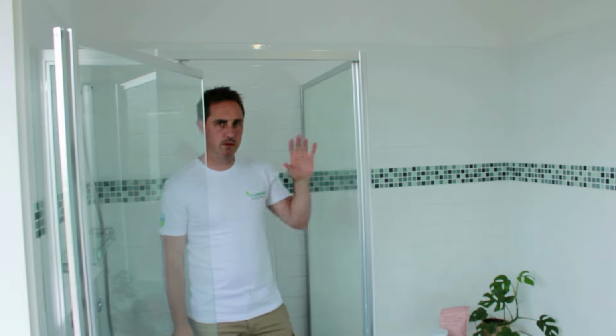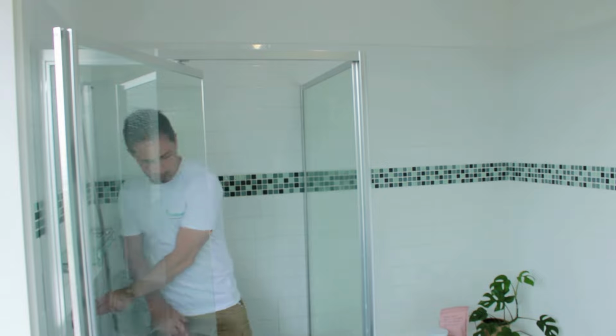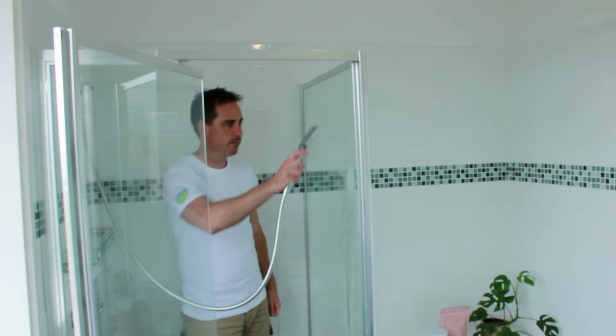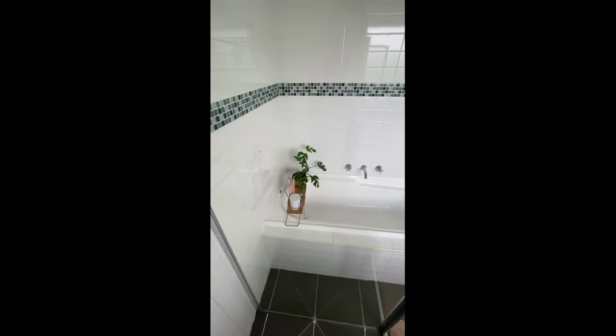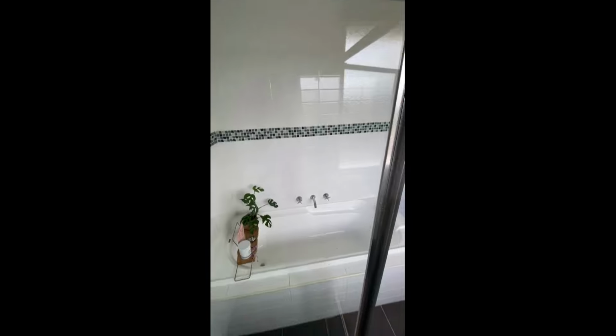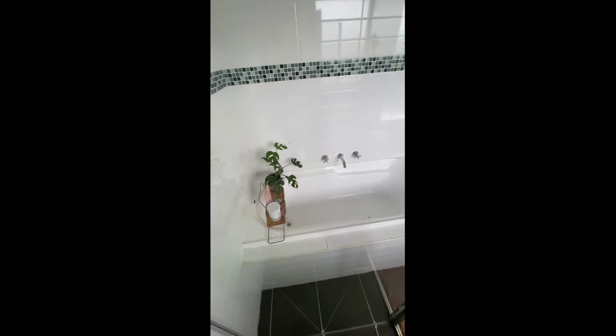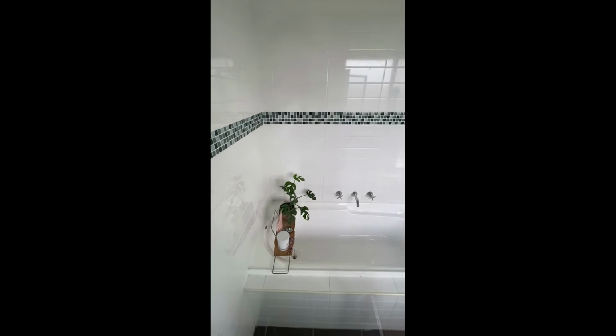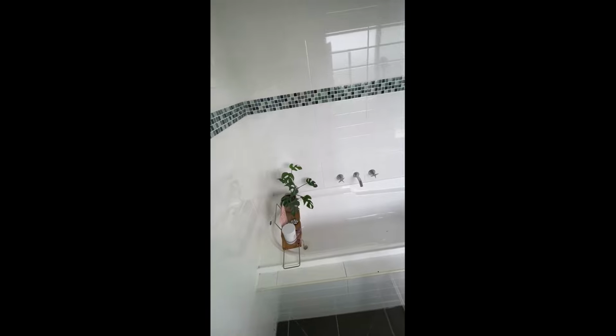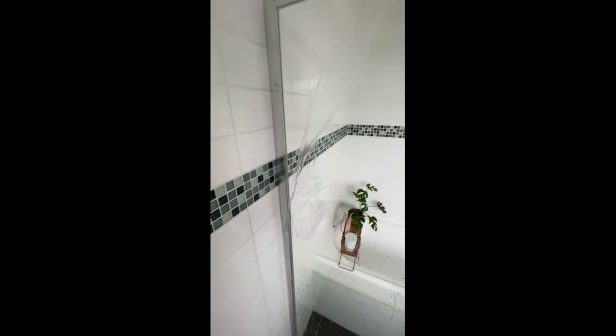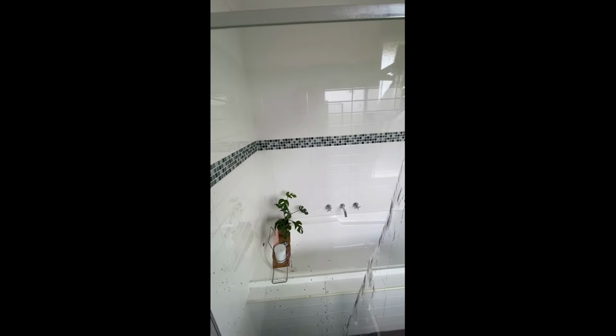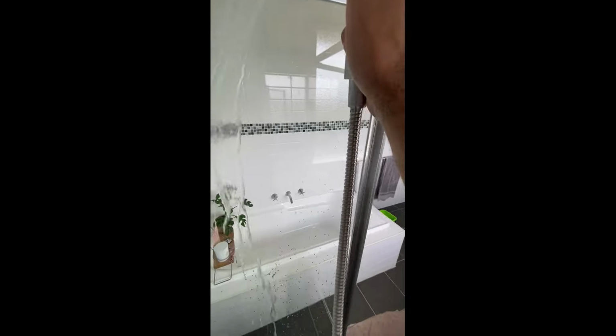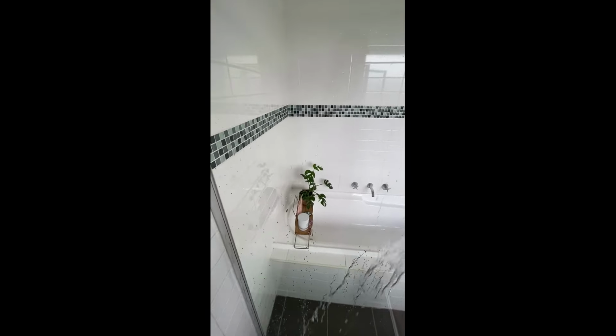So now that we've been through that sort of 20-minute cure time, now it's just simply a case of running water and rinsing off the ClearShield, and then just wiping off the excess resin, and then we'll show you the after effect of exactly how the glass behaves. So as you'll see now, not only is the glass a lot clearer than it was, we'll put some water on it and show you the difference with the glass now upgraded to ClearShield non-stick Eco-Glass. And just notice as the water hits, nothing's sticking to the glass, and that water will just run straight off.